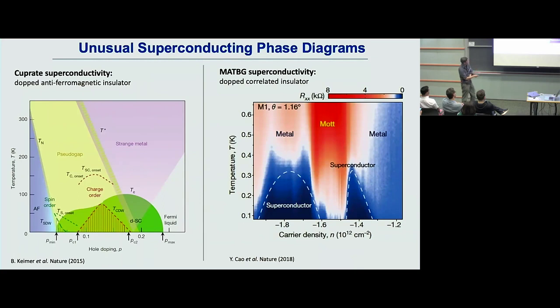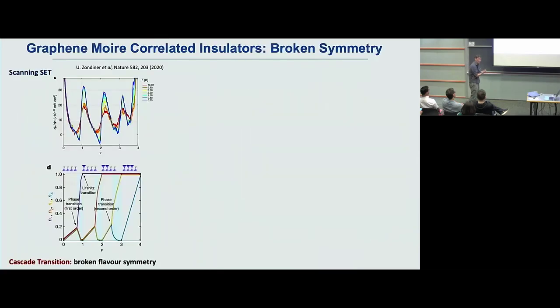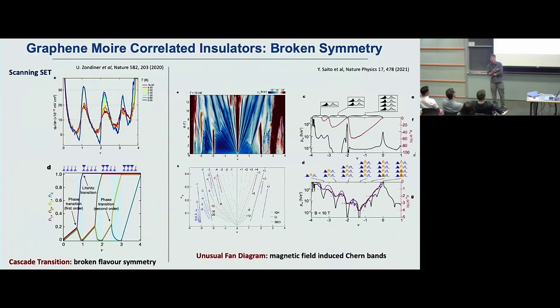It becomes clear that although it's interesting, in the very first paper it was marked as a Mott, but now we don't call this Mott, because we now know, as mentioned a couple of times throughout this workshop, that all these broken symmetry states sometimes actually have a topological character. It turns out many of the insulating states, which are the parent of this superconducting state, are in fact topological. Often the Chern numbers or valley Chern numbers can be associated with them, which is a marked difference from the cuprate physics in some sense, right?